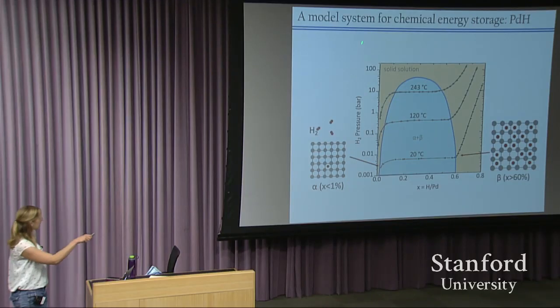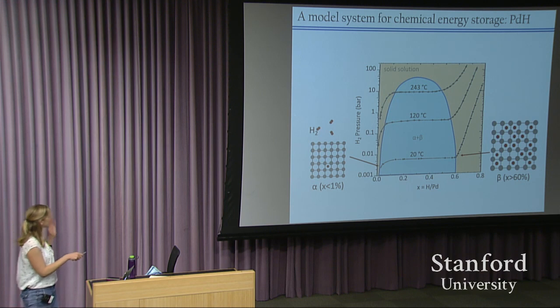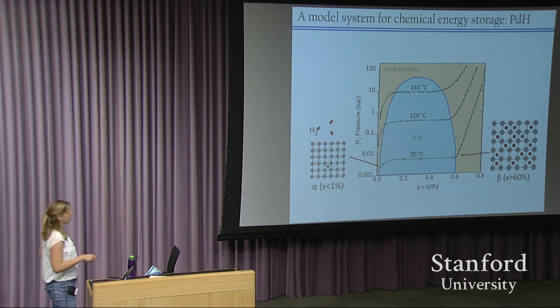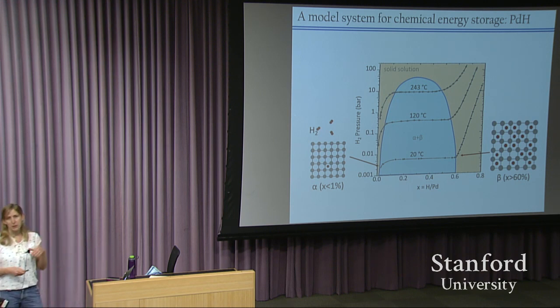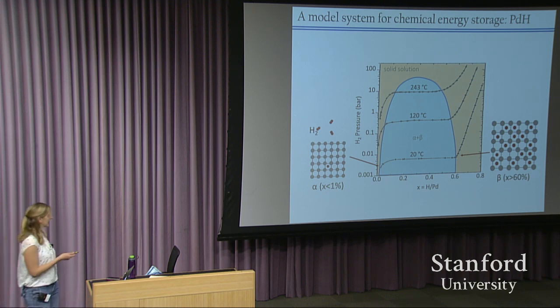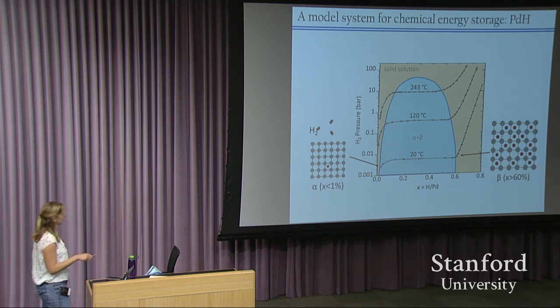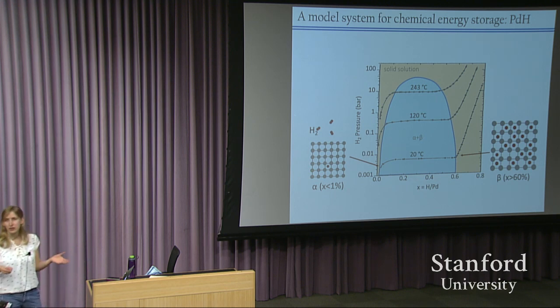So I'm plotting the hydrogen gas pressure on the vertical axis, as a function of the concentration of hydrogen per palladium, so the number of hydrogen atoms per palladium atom in the crystal lattice. And you'll see that at low hydrogen pressures, the system basically exists in the alpha phase. It's a dilute interstitial solid solution.